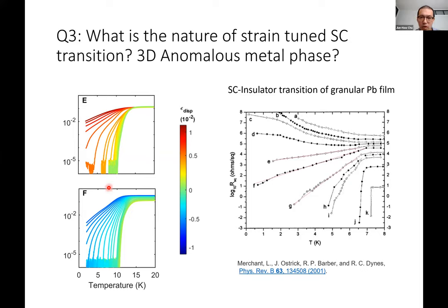And now we have a new way to continuously switch the superconductor on and off. And then very interestingly, near this superconductor-metal quantum phase transition, this very broad transition where we see a linear temperature dependence in the log of resistivity, this has actually also been seen in the superconductor-insulator transitions in